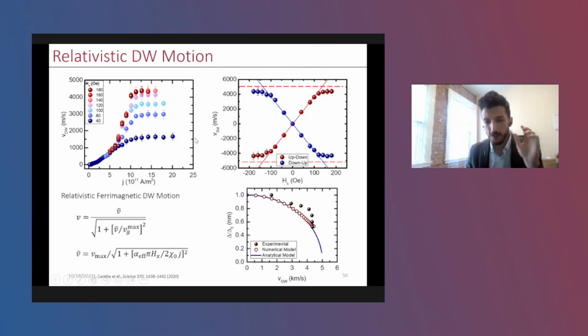Yeah, good question. Let me see if I can find it for you. We don't measure it directly. If you look, you essentially normalize the maximum velocity that you're currently at to some control velocity at low field where you see the saturation. If you look at the paper, it's more directly in there. If you do this sort of ratio, a lot of things cancel out, and you can estimate a normalized domain wall width just from the data that you see on the screen. So we're not measuring directly, we're just inferring it from the experiment. It's basically a sanity check to make sure that the contraction we're inferring agrees with what we're seeing from the model, so that the saturation isn't in fact coming from some other effect. It's in fact from the source. It's more of a sanity check thing.